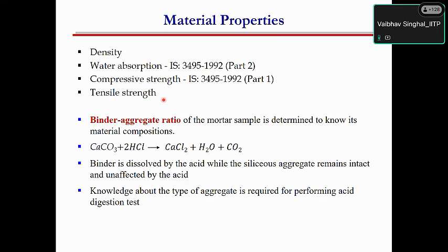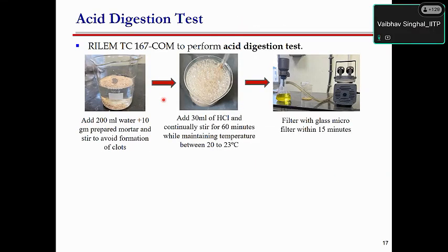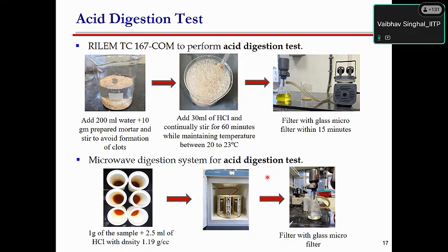To find out the binder aggregate ratio, there are some simple tests. One of the tests which is very popularly used is the acid digestion. The concept is simple. In the acid digestion, whatever material is inert will not dissolve in the acid, whereas the binder, which primarily consists of lime, will get dissolved in the acid. There is some specialized equipment and some simple chemicals like HCl that you can use. By using this test, you can find out the proportion of binder and aggregate. Either you can do a simple acid digestion, or you can also use a microwave digestion system to get the results much quicker.